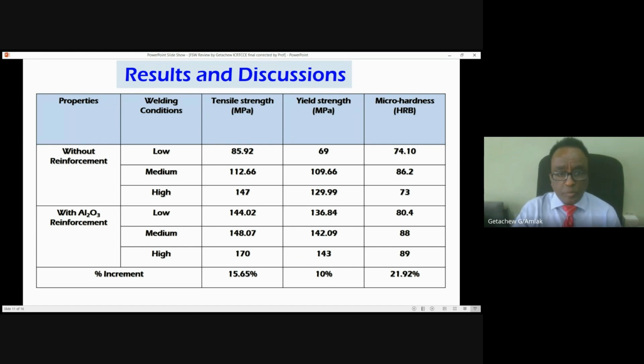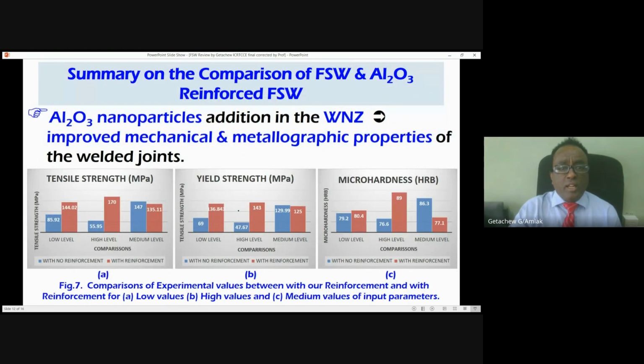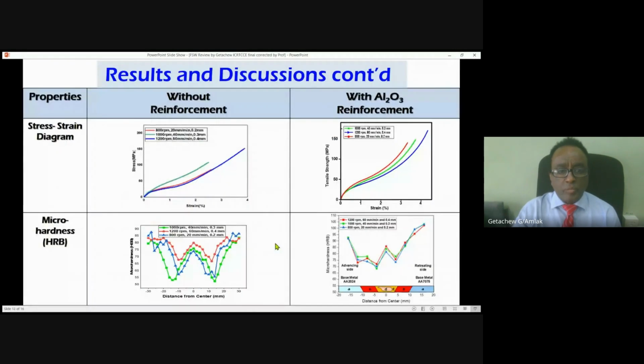on the weld region. When it comes to the summary, the addition of the alumina particles in this experiment has shown much improvement in the mechanical and metallographical properties. It has been summarized in table form accordingly. Here we can see the stress strain diagram shown for the comparison between without reinforcement and with reinforcement. And when it comes to the micro hardness HRB, this is a W profile that is shown when the hardness is measured further distance from zero in both directions. So we can see the pattern and the values accordingly. We can appreciate the change that is made due to the addition of the alumina particles.